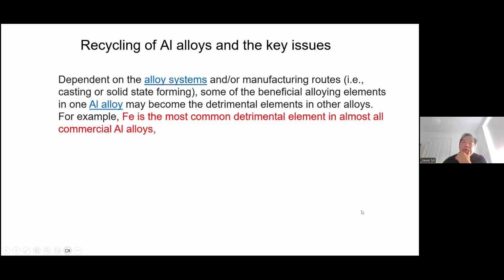So what's the key issue in recycled aluminum? One key thing is that if you recycle the materials through many cycles, you accumulate a lot of contamination from different elements. Some of them, of course, are beneficial, but for most of them, over a number of recycling cycles, the element level will exceed the design level of the normal alloy. So that will lead to a lot of detrimental structures, phases or defects forming in the recycled aluminum materials.